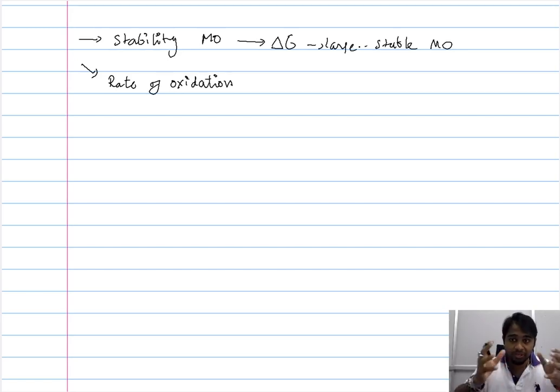Therefore you introduce a selective oxidation, meaning the elements with a large change in the free energy, or more stable metal oxide, will form, and when this forms and occupies the surface, this stable metal oxide prevents the exposure of the underlying metals.